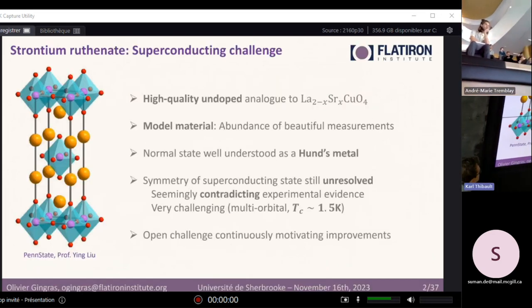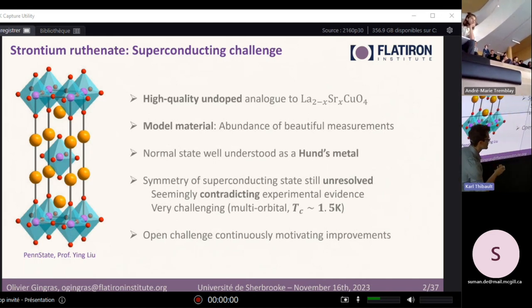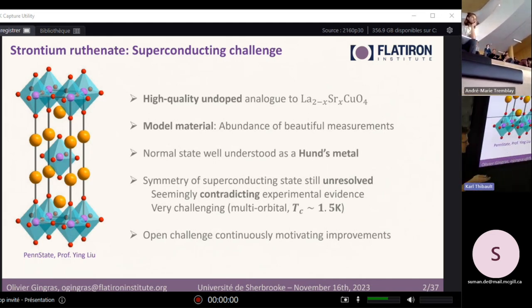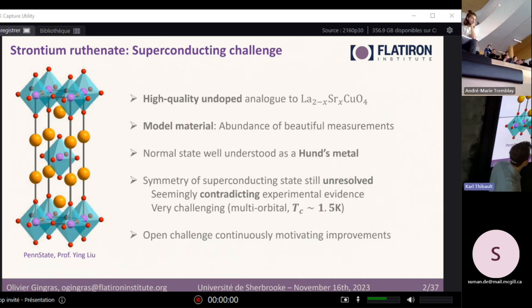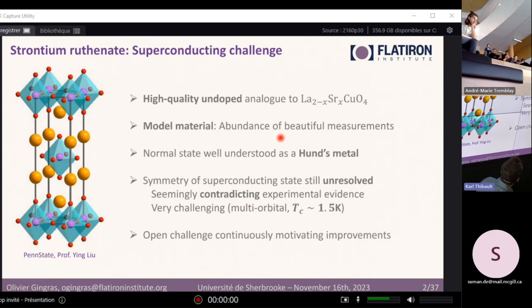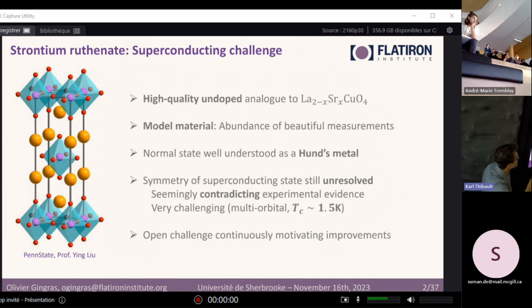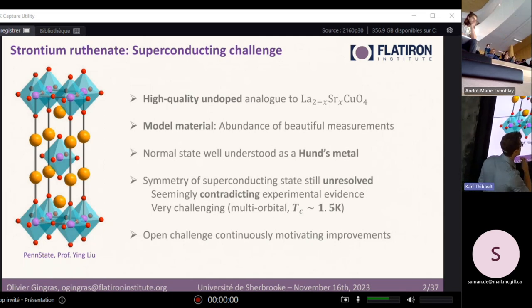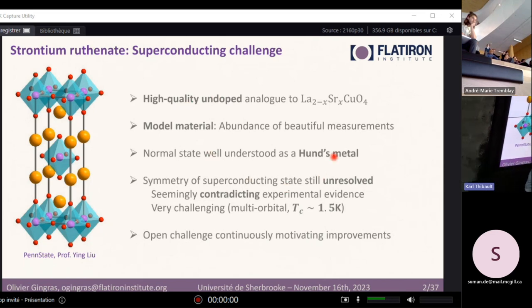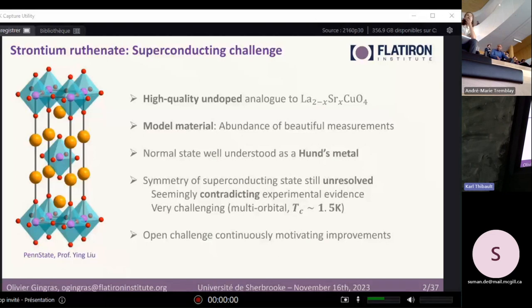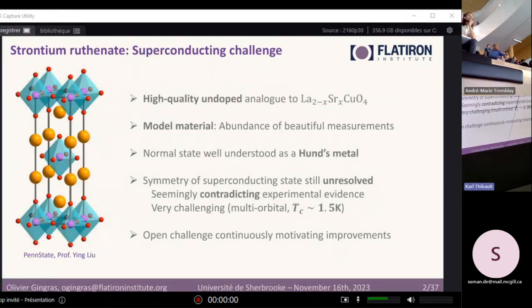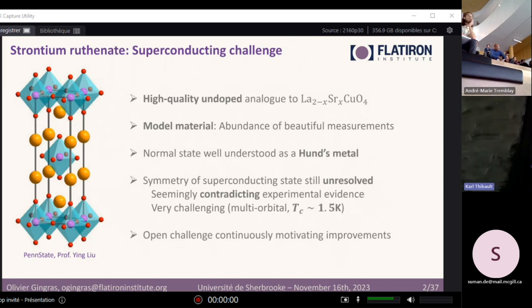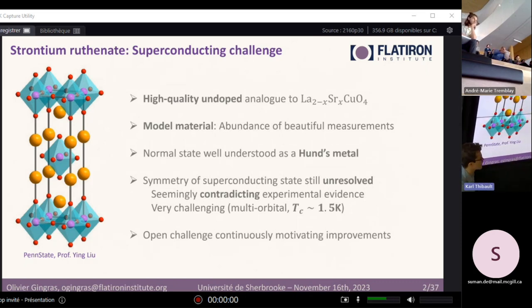For those who don't know strontium ruthenate very well, I'm going to do a pretty long introduction so that you know what André-Marie summarized in a few sentences. Strontium ruthenate is a high-quality, undoped analog of the lanthanum copper oxide superconductor. The point is that it can be superconducting without being doped. That led to extremely good quality samples and very beautiful measurements. Because the samples are so clean, in this material every probe was used on either the normal state or the superconducting state. And so now we have really the best measurements with no corruption from impurities.